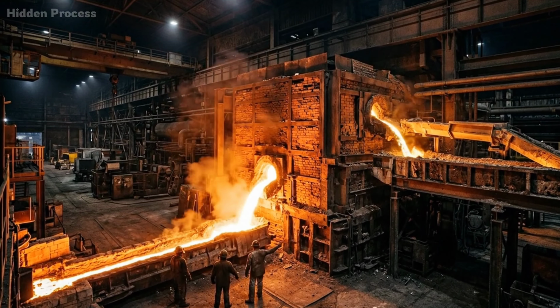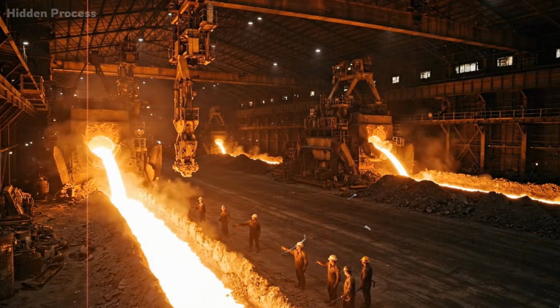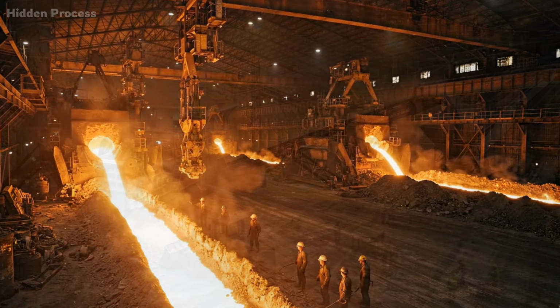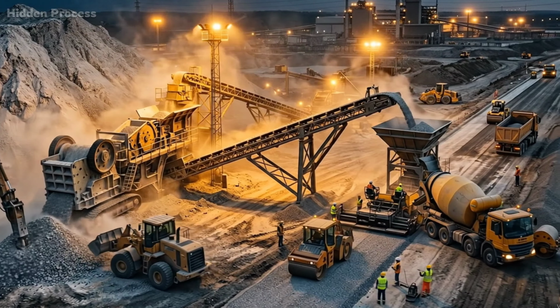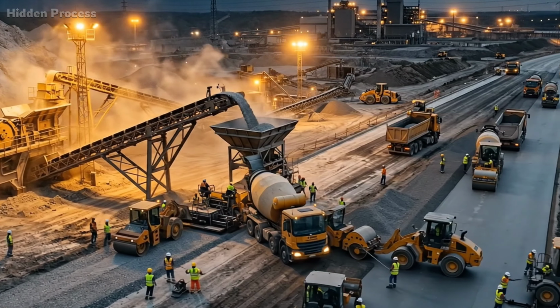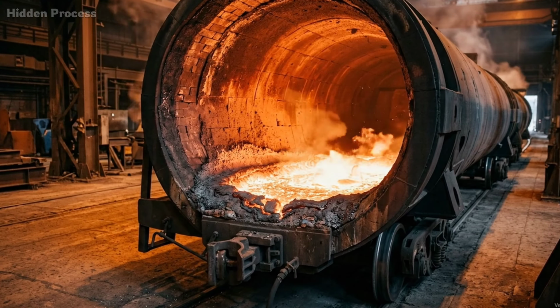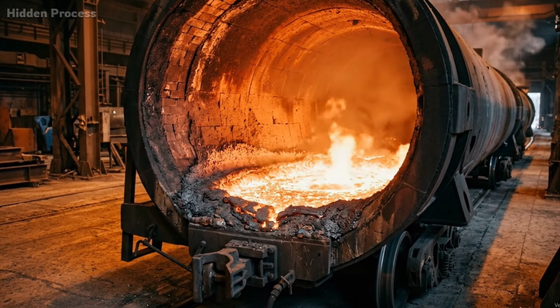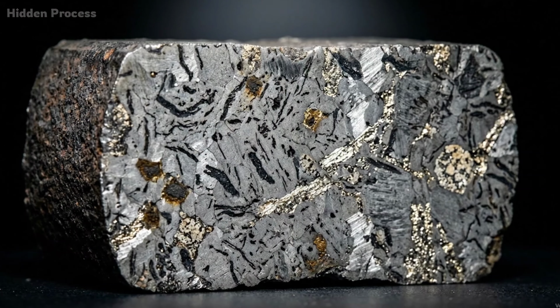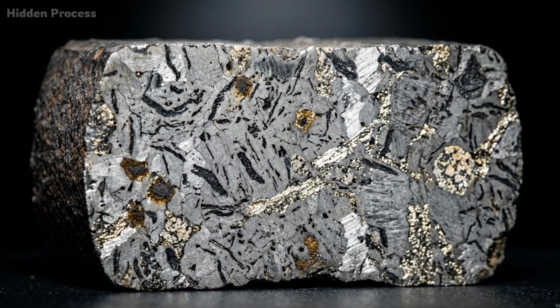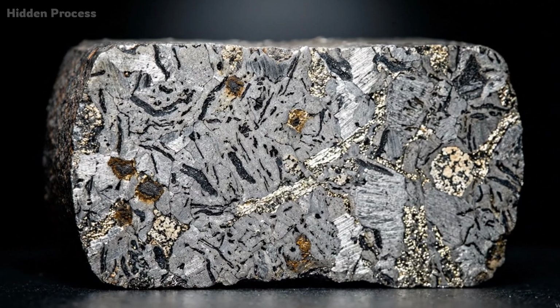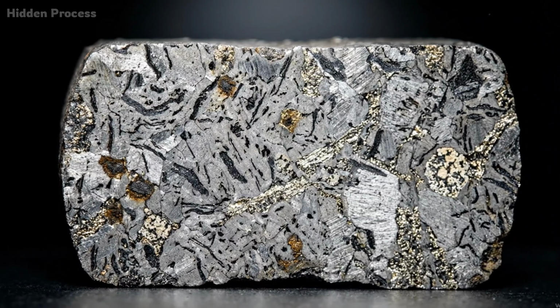The slag, being lighter, is tapped from a separate hole above it and directed away to be cooled, crushed, and repurposed as road construction material or cement additive. Nothing is wasted. The liquid iron at this stage is called hot metal or pig iron. It contains about 4 to 5% carbon, along with traces of silicon, sulfur, and phosphorus.